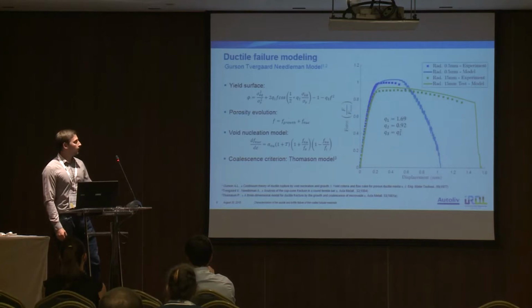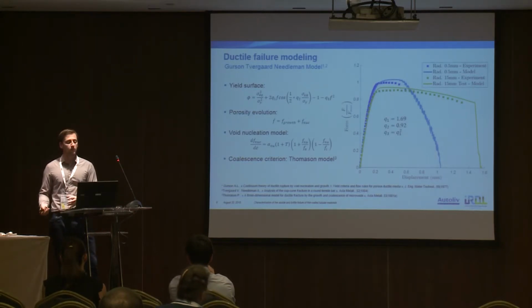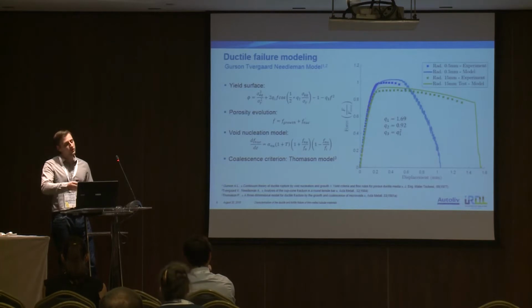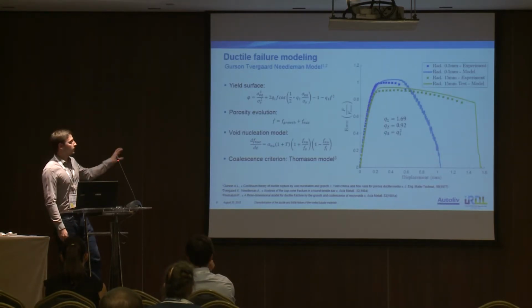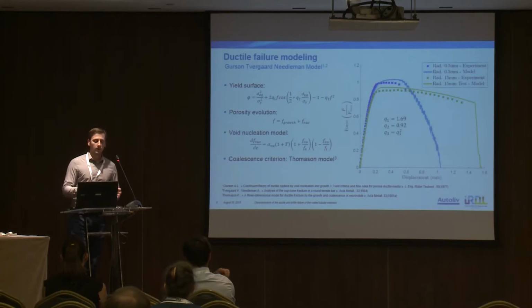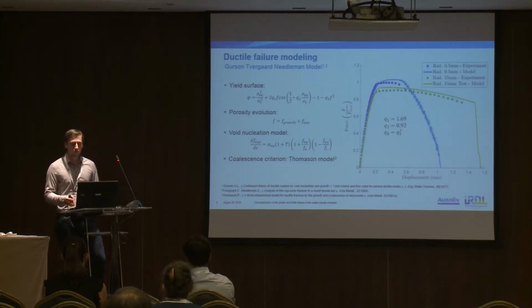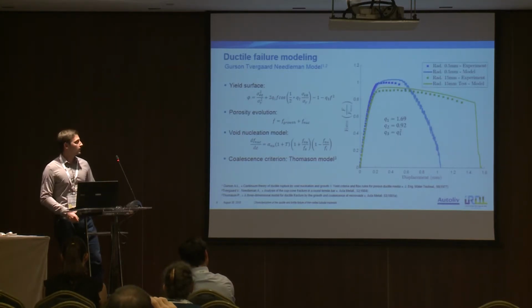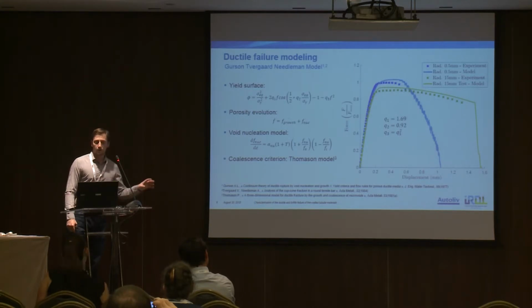And then we define a coalescence criterion with the Thomason model. This is not a strict criterion, because it's not possible to find a critical value for such a criterion. It's an implicit criterion. Then, using this model, we inject these equations inside a finite element analysis simulation, and we compared the experimental results to the numerical simulation results. As you can see here, the fits were quite good.